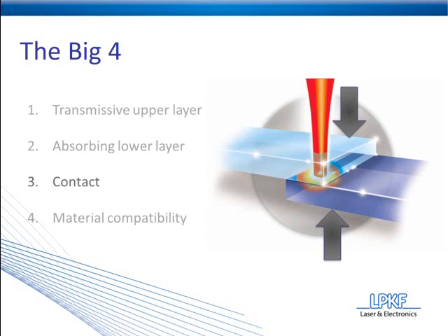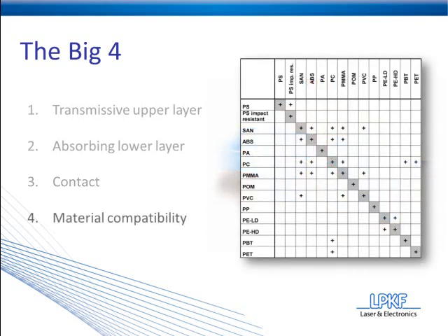The final factor is material compatibility. The two pieces of plastic to be joined need to have similar resin properties as well as similar melting temperatures. If the melt temperatures of the plastics vary too greatly, then one piece of plastic may react very well to the laser radiation, while the other piece is left completely unaffected or actually burning.